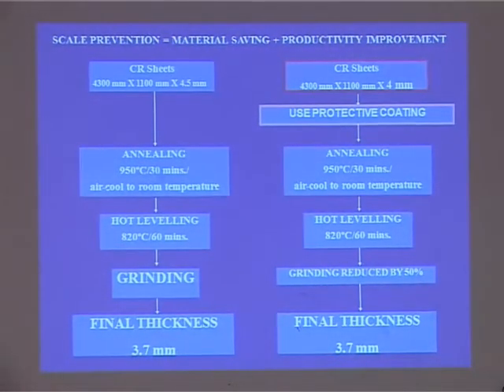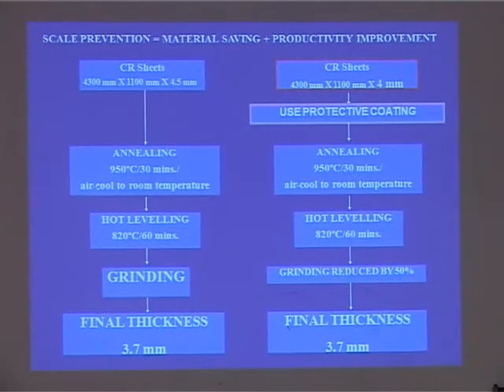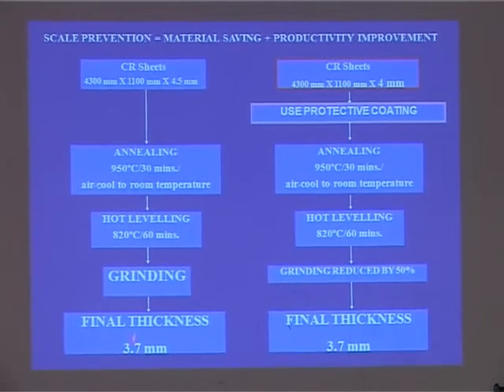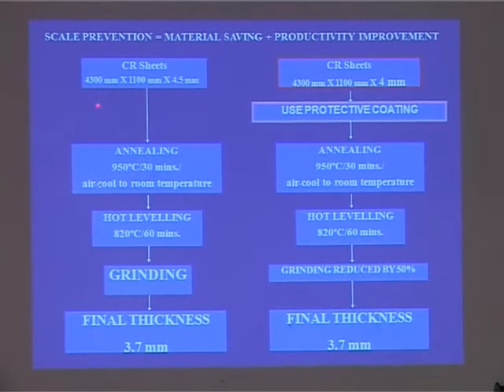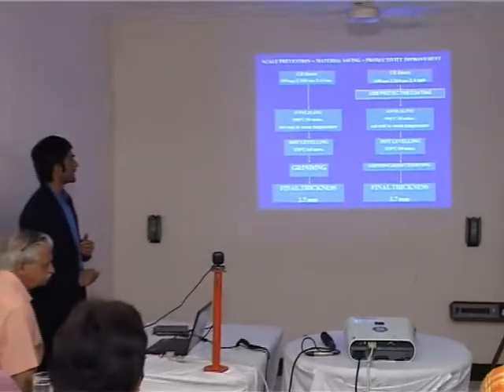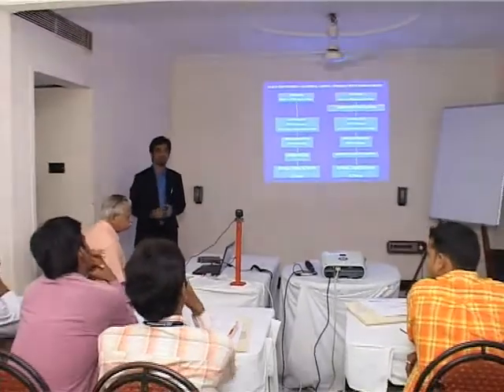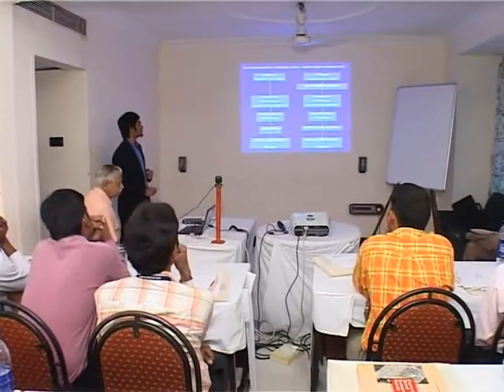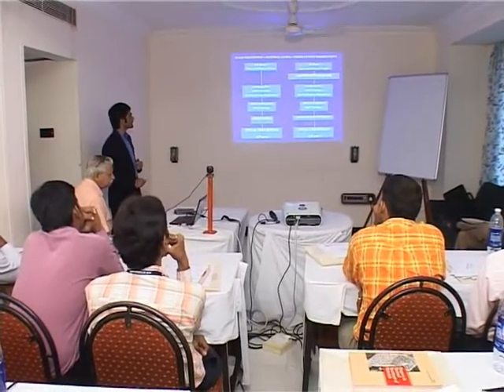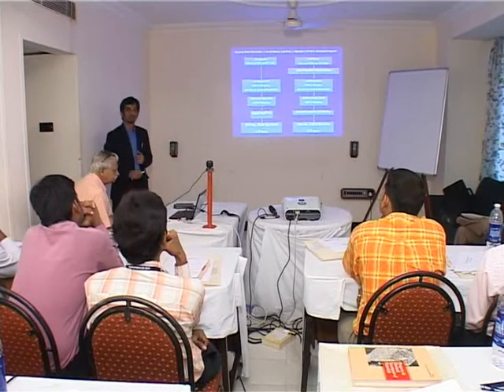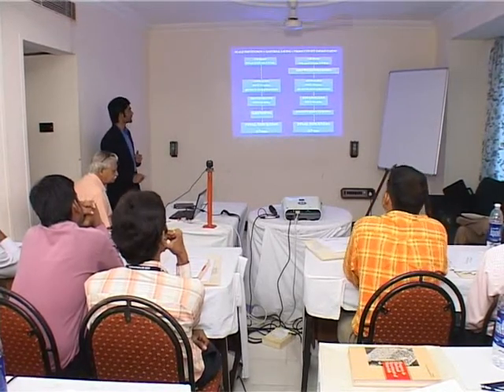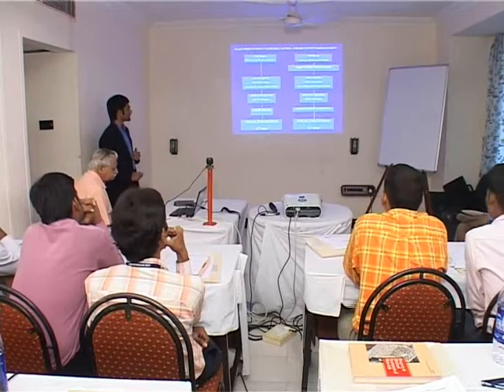This is an interesting case study in case of alloy steel, quite an expensive one, where the final thickness that was desired was 3.7 mm, and they started with an initial thickness of 4.5 mm. The remaining portion was left for grinding, which accounted for loss due to scaling. Now this is quite an expensive alloy steel, and after using an anti-scale compound, after trials, we came to a conclusion that the allowance could be reduced up to 4 mm. That is, we could reduce 0.5 mm from the initial thickness, and the use of protective coatings before charging them into the furnace. Annealing, the cycle time, everything is the same.